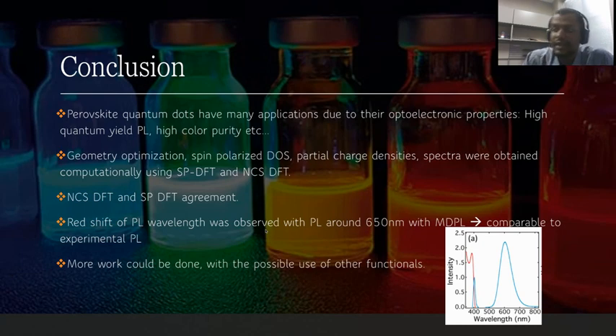And we also discussed a little bit on the crystal field theory, and I forgot to mention that from the molecular dynamics video, the manganese, supposedly liking to be octahedral, was shown to prefer tetrahedral coordination. So that would translate maybe into a tetrahedral split, or maybe not, or maybe it's because of the size of the ion or the ionic radius, and also because of the ionic interactions, I guess, that they would prefer that coordination.